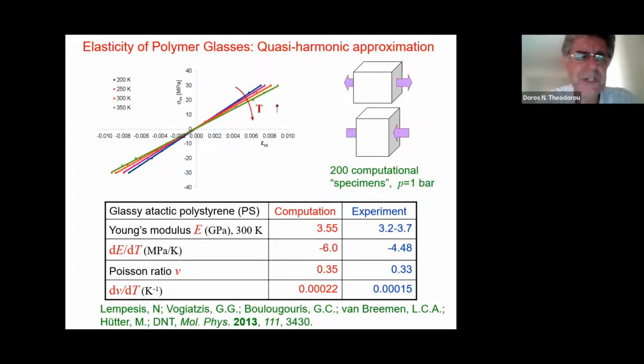You have, in other words, elastic response out of the material. So from the slope, you can calculate the Young's modulus, and from the lateral changes in dimensions of the specimen, you can calculate the Poisson ratio. And here are shown these as calculated from the quasi-harmonic approximation imposed on the many configurations of glassy polystyrene that we generated.